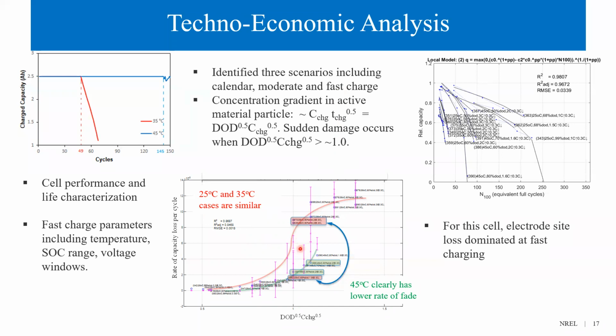Sudden damage occurs, and the rate of capacity loss significantly increased, as can be compared by the testing condition in the red box. Fast charging at 25 and 35 degrees Celsius, the loss rate was similar. At 45 degrees Celsius, a lower rate of fade can be achieved. Model regression indicates capacity fade at fast charging cycling is caused by electrode site loss. At moderate cycling, capacity fade was mainly due to lithium inventory loss.